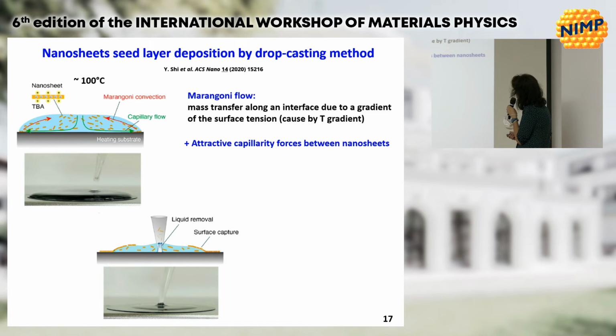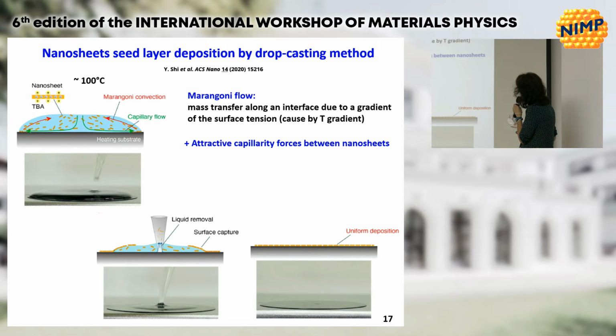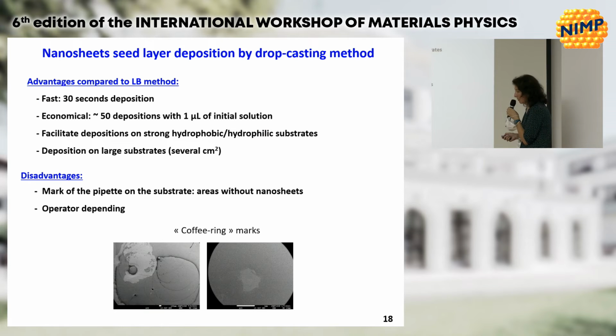And finally, we have a shrinkage of the droplet. So here, this film is deposited on the substrate. And finally, when the liquid is entirely removed, we have a uniform deposition of nanosheets on the substrate. This method is really interesting because it's very fast. It's very economical because we don't have to use so much solution, so we don't waste materials.